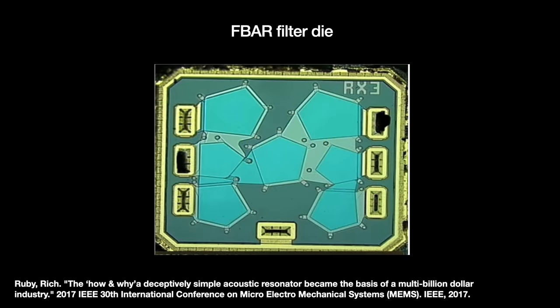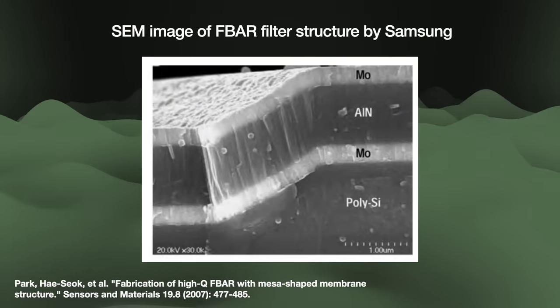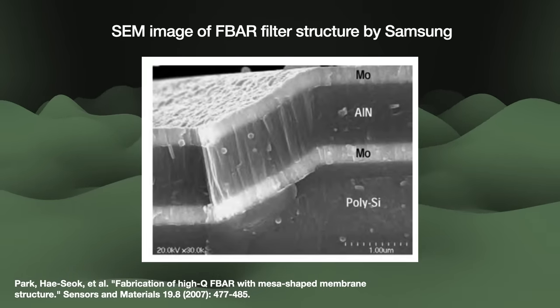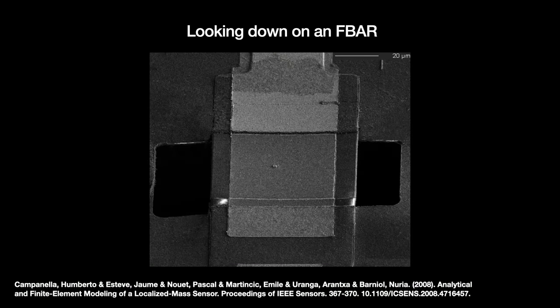But there was one big downside: they're harder to make. We still produce these FBARs using advanced MEMS technology, and FBARs have far more complicated structures than SAW filters. The piezoelectric layer is often made from either aluminum nitride or zinc oxide and must be very thin, and depending on the substance it might be difficult to produce a good, even layer. The complexity manifests itself in the increased number of mask layers. An SAW filter takes one, maybe two to three mask layers tops. But a good FBAR filter will take 9 to 13-plus mask layers.